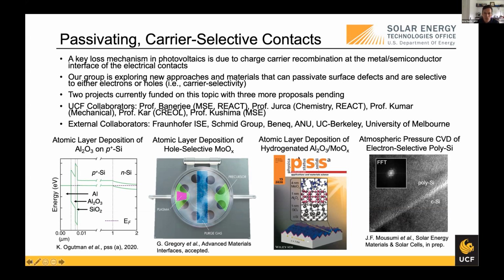And then just recently we got on the cover of PSSA with some work looking at hydrogenated aluminum oxide, moly oxide kind of film stack that we're now coupling with transparent conductive oxides that can be used on the front side of a solar cell. And that work's been done in collaboration again with Professor Banerjee and Professor Jurca.